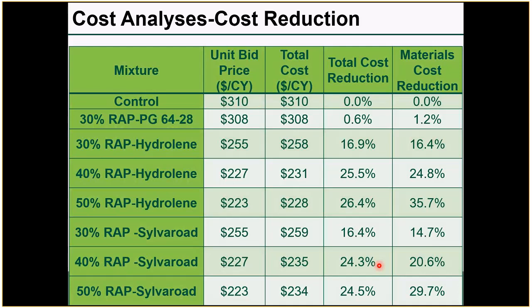But in terms of price for the contractor, it's not worth it because the cost saving is less than 1%. And the main reason for that is really the cost of that binder, the PG64-28, which is more expensive than the 64-22. So the savings is not that much, and that's what you see. We did our own material cost. Based on the proportions there, we also did an evaluation of the cost of the material itself, not the bid. And again, it's very similar to what you see in the bid reduction.